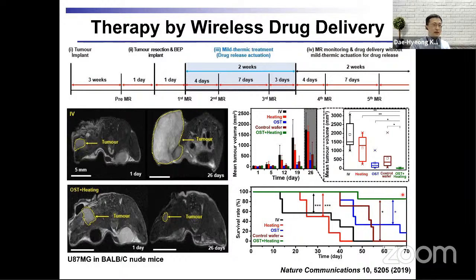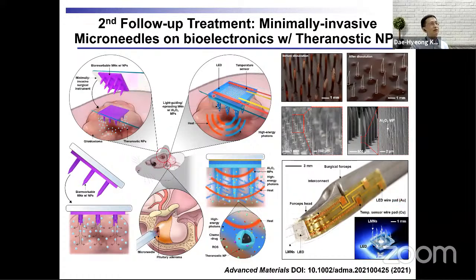But still, we have a 20% decrease, and that means that tumor regrowth can occur. So more recently, we developed a second follow-up treatment method by using minimally invasive microneedles on bioelectronics with theranostic nanoparticles. In this case, we integrated the microneedles and flexible bioelectronics on the surgical forceps. If you see the scale bar, the thickness of the surgical forceps is very thin.